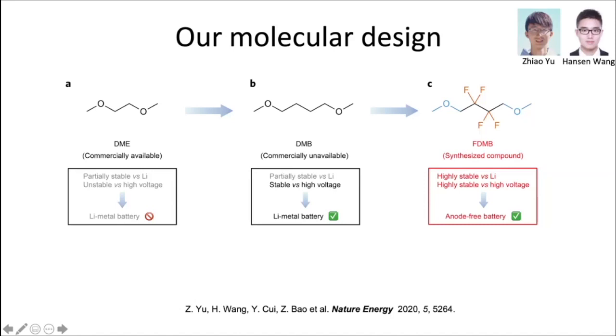The traditional ether solvent has this DME structure. We asked the question: if instead of two CH2 groups, we extend that to slightly longer, what will happen? We found that this actually improved the oxidative stability. And then further, we added CF2 groups, which are electron withdrawing groups, supposed to further pull the electron away from the oxygen. And how is that going to impact the lithium metal